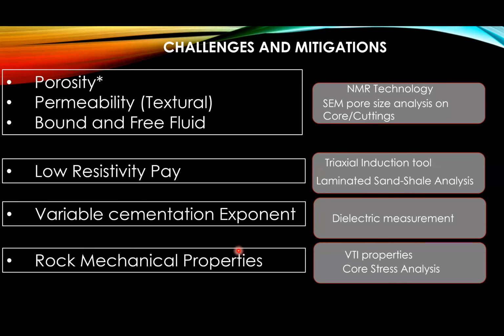And then finally, the rock mechanical properties. Here we propose to use VTI properties, but again, it's more on the analysis side, not on the tool side. For the tool, you ideally measure a dipole sonic tool with a Stoneley, and then by calculating, we can actually come up with a VTI property. So VTI is vertical transverse isotropy. That basically takes into account the layering effect. So the layering effect is quite significant. We'll look into that.